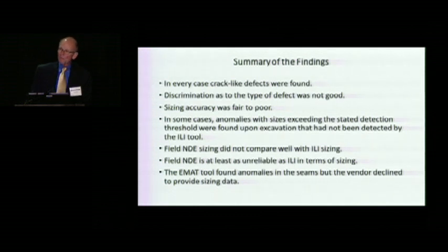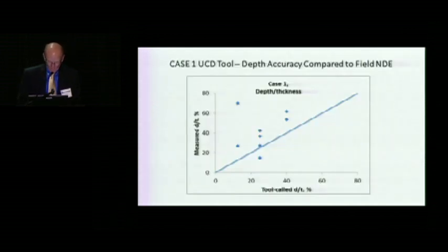Now, the other thing we found was that field NDE or in the ditch methods did not compare well with ILI measurements in some cases, and we found out that these in the ditch measurements probably aren't as reliable as the ILI. Now, the EMAT tool found anomalies in the seams, but because the primary purpose of the EMAT tool run was to find stress corrosion cracking, the vendor in that case at that time would not provide sizing data. And you can't blame them, they weren't tasked with doing that.